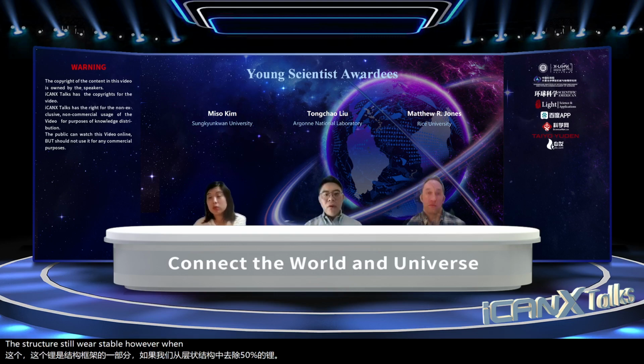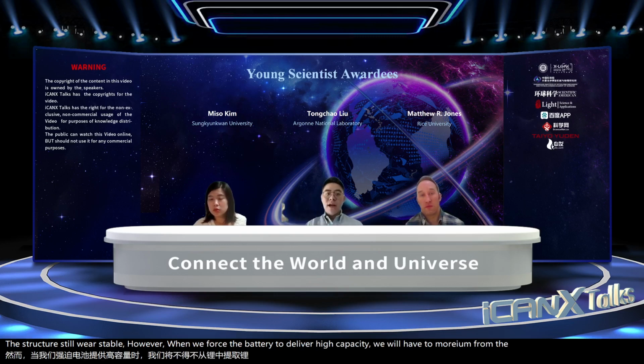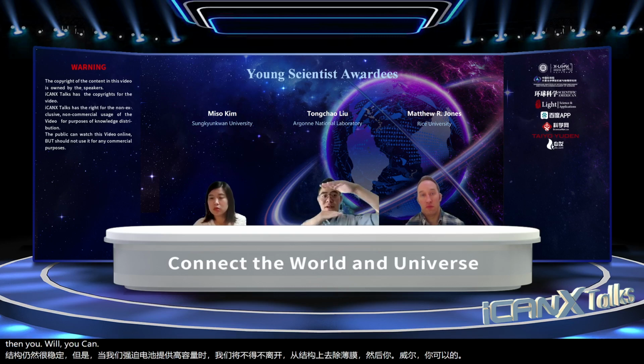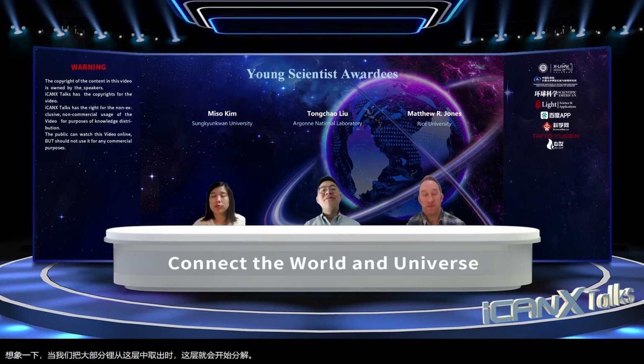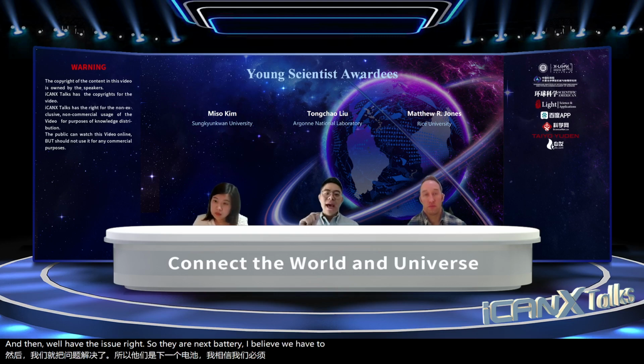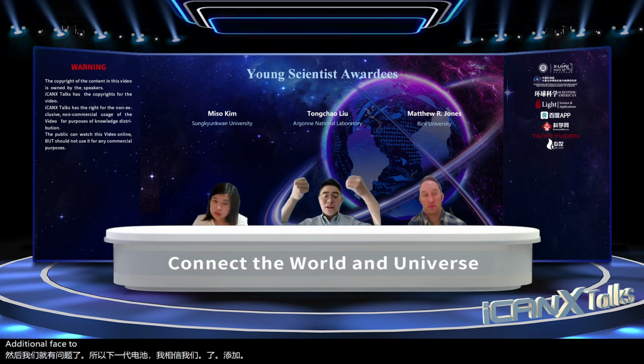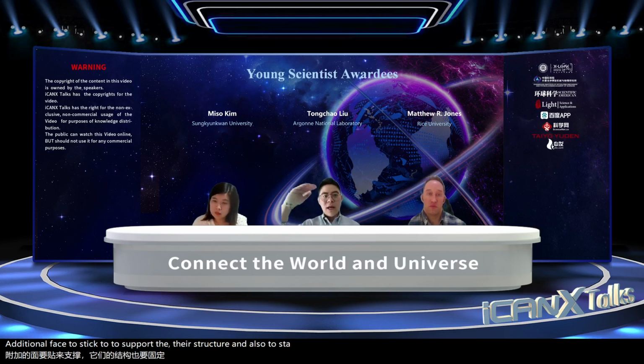However, when we force the battery to deliver a high capacity, we have to remove more lithium from the structure, and you can imagine that when we remove most of the lithium out of the layer, the layer will start to decompose, and then we have the issue, right? So for the next generation battery, I believe we have to add an additional phase to support the layer structure and also to stabilize the structure framework.